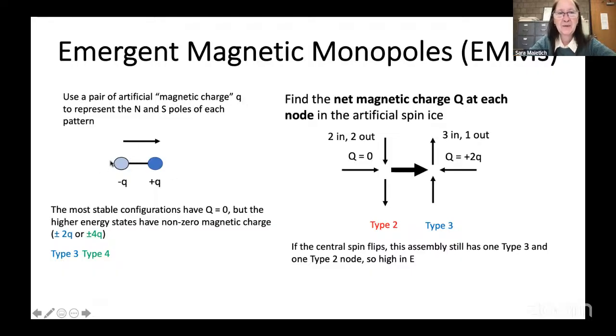charges, plus and minus, so that you have a dipole here. This is fake charge of the North and the South Pole. But overall, you have net charge 0 for the dipole. Now, if you look at a node where 4 spins or 4 dipoles meet, and you sum the total charge at that node, if you follow the ice rule, 2 spins in, 2 spins out, the net charge is 0. So this is a stable state. This turns out to be a type 2 node. But in some cases, you have, say, 3 spins pointing in and 1 spin pointing out. You have a net charge at this node, and so that's an unstable state or a higher energy state. This is what is called the monopole, whether it's type 3 or type 4, that's considered a monopole.